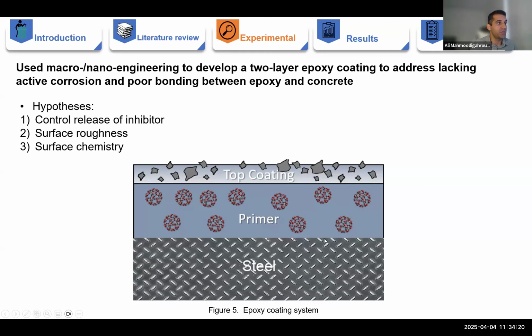For the first layer, which is primer coating, we hypothesized that if we can have some smart nano reservoirs that can release active agents only when it's needed, we can solve this problem. Basically, these small nano reservoirs are selective. They don't react with calcium hydroxide, and they're only responsive to corrosive species. They keep monitoring for the presence of chloride ions, let's say, and then when they're exposed, they will be triggered and release active agents in the coating.